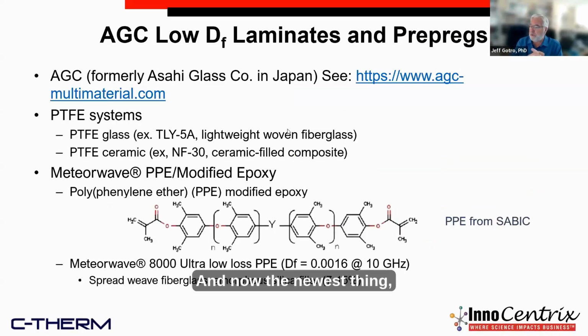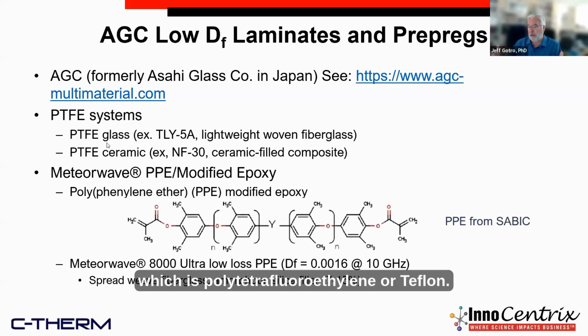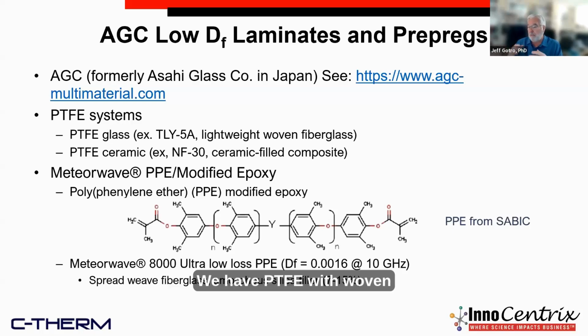And now the newest thing, as we talked about, driven by the 5G cell phones, are very low dissipation factor laminates and prepregs. And we have PTFE systems. So they have PTFE, which is polytetrafluoroethylene or Teflon. We have PTFE with woven fiberglass. We have PTFE with ceramics. But PTFE is very difficult to work with. It has a very high melting point. And when it does melt, it has a viscosity of lead at room temperature.